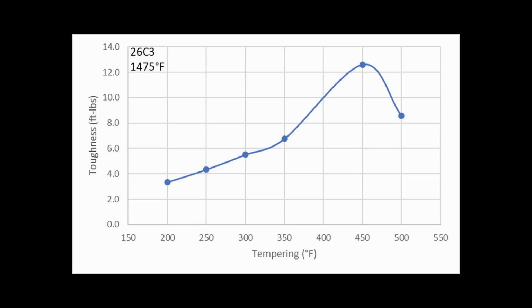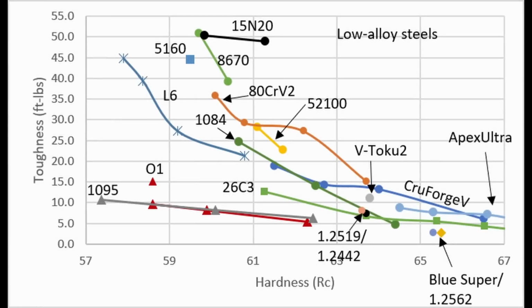Would be an interesting thing to look at, but for our purposes, 15N20, really high toughness, especially when you temper between 350 and 400 degrees. And this thermal cycling procedure that I did seemed to work really well. Now, 8670 is somewhat more complicated.